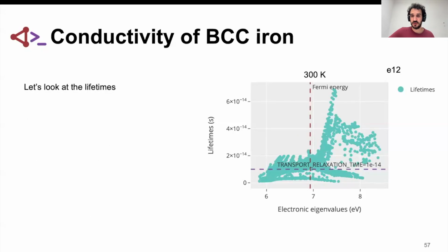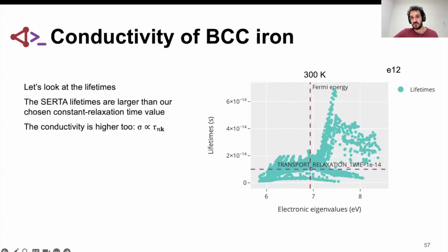Let's look at the lifetimes. Here are different lifetimes that we needed to compute that enter in the transport distribution function. The horizontal line is the transport relaxation time that is set by default in the INCAR tag, in the INCAR file, and is 1e to the minus 14 seconds. What we see is that the lifetimes computed from self-energy relaxation time approximation are higher than the constant relaxation time that we set. And that, of course, means that the conductivity will be higher too.